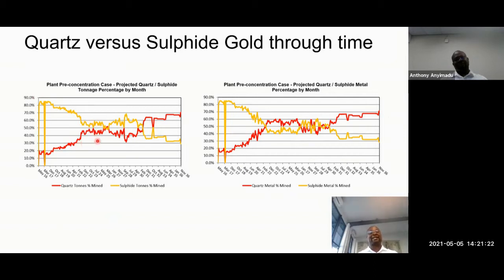But as the mining gets deeper in this place, the quartz gold, which is the easy gold, actually becomes about 60%, sometimes even close to 70%. So whatever opportunities we identify and use here would actually be better as time goes by. So that's what we're saying: this is not some fluke sample we took and said, oh, let's change the whole circuit because of that. From the geology and from the material horizon expected over 30 years, we see that that trend is continuing.